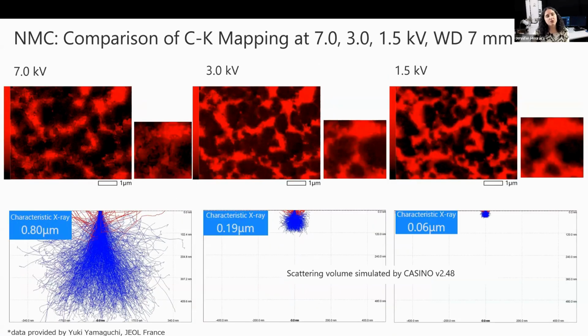So now, if we take a closer look at the carbon maps from these 3 studies, along with Monte Carlo simulations, the depth of penetration using that standard signal depth feature for each accelerating voltage is located on the top left of each simulation. So it's easy to see why we get this improvement in surface sensitivity and resolution of the binder material by reducing the accelerating voltage, since what we're doing is reducing the depth of penetration of the beam from 800 nanometers into the sample down to about 60 nanometers. So at the lower kVs, we'll not be picking up much of the sample below the binder itself.